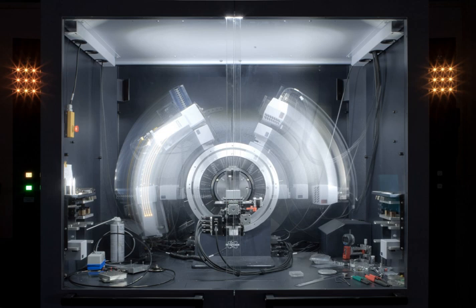Protein crystals are scooped up by a loop, then flash frozen with liquid nitrogen. This freezing reduces the radiation damage of the X-rays, as well as the noise in the Bragg peaks due to thermal motion, the Debye-Waller effect. However, untreated protein crystals often crack if flash frozen, therefore, they are generally pre-soaked in a cryoprotectant solution before freezing. Unfortunately, this pre-soak may itself cause the crystal to crack, ruining it for crystallography. Generally, successful cryo conditions are identified by trial and error.